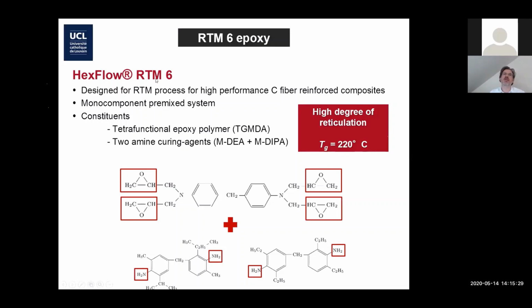Okay, so I will not spend too much time on the chemistry of the RTM6 resins. RTM means resin transfer molding, so it's one of the preferred methods to produce high quality composite parts, used a lot in the aeronautic industry. And this specific resin is not anymore the best one. There are better ones, but it's a typical resin for carbon fiber reinforced polymers that I use quite a lot in aeronautic applications. There are better resins today with higher performances, higher fracture toughness, but still. It's a tetra-functional epoxy, meaning that there are 4 functions here that can link to a highly reticulated material. The Tg is above 200 degrees C, which is important. It means that room temperature will be very far from Tg, meaning limited viscoelasticity.